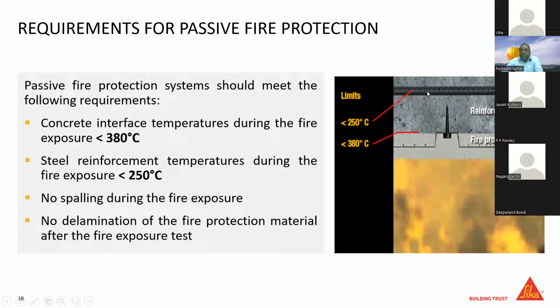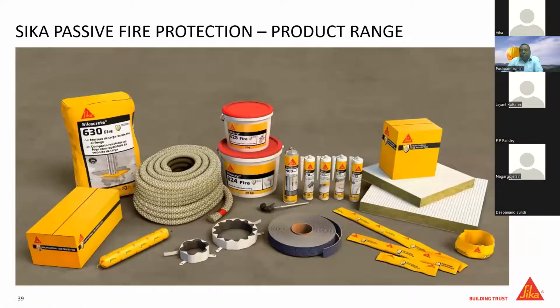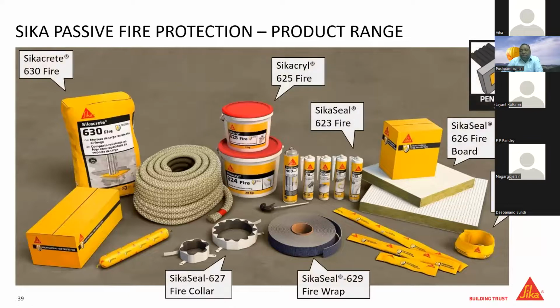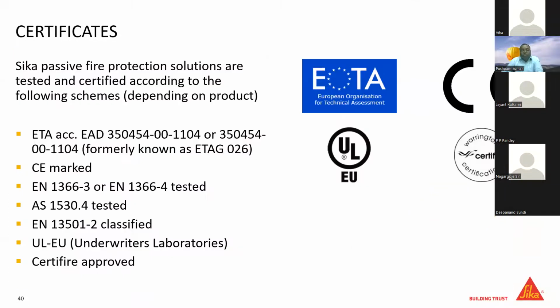This should hold even for a fire of 1200 °C; in case the fire is of 1200 °C, the temperature should not exceed 380 or 250 °C at the concrete interface or steel reinforcement. There are various systems available, like penetration seals and linear seals, for controlling the fire and confining it in a closed location. These fire protection systems are certified as per various international codes, like European codes or UL standards, against which they are designed and the fire rating is given.